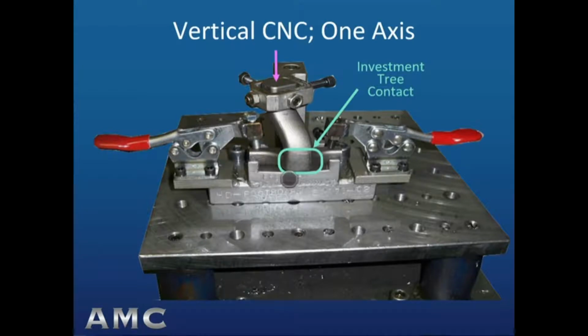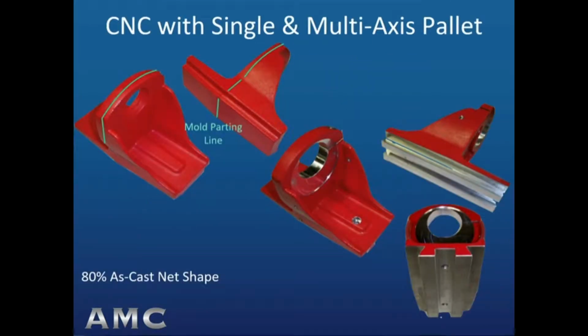Note, once again, the investment mold tree connection shown in the blue-green oval is avoided in the fixture design. This is an interesting example of a more complex machining in 3 planes, but accomplished with a simple single-axis CNC setup, followed by an innovative multi-axis pallet setup on a horizontal CNC. The images at the upper left are the as-cast surfaces, and those at the lower right are the finished machined part. Despite being machined in 3 planes, the casting's final net shape is still about 80% as cast.